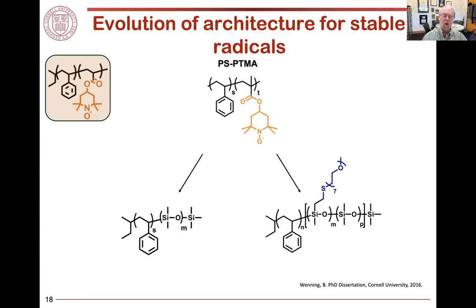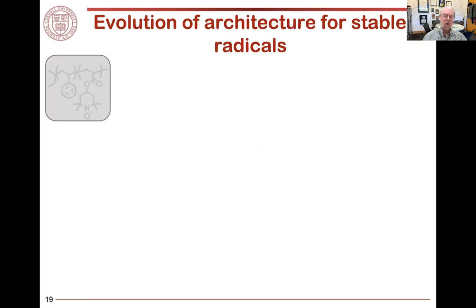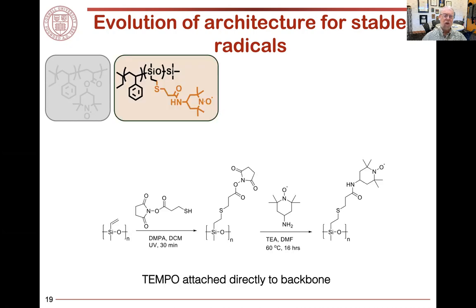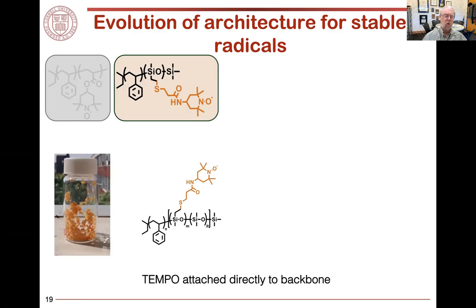And so we can incorporate it in our coating, but to get it to populate the surface, we have to use it at such a high concentration that the materials really didn't behave well enough to be a long active coating. So our next choice was to take PDMS and modify the backbone with TEMPO. We used a variety of the thiol-ene click chemistry I described before, and then we activate an acid with a succinimide group, and then we can attach an amine functionalized TEMPO and incorporate that into the backbone. And the chemistry works well. We end up producing a polymer that has the notable orange color of the TEMPO unit.